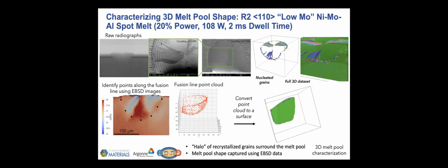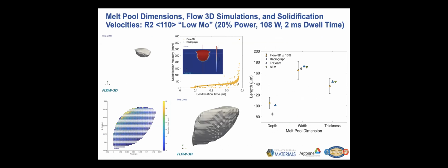One interesting thing about this particular data set is we saw this halo of grains present at the melt pool edge, and then these columnar grains that emanate from that, which I'll talk about in a second. But again, the important point is we get the 3D melt pool shape. So here we're now directly comparing some Flow 3D simulations. These are multi-physics simulations that include conduction and convection. And we're directly comparing that to our radiography. So here we have solidification velocity versus solidification time, and we're comparing Flow 3D versus the radiography. This gives us a benchmark to compare those velocities to make sure that the modeling is matching the experiments.